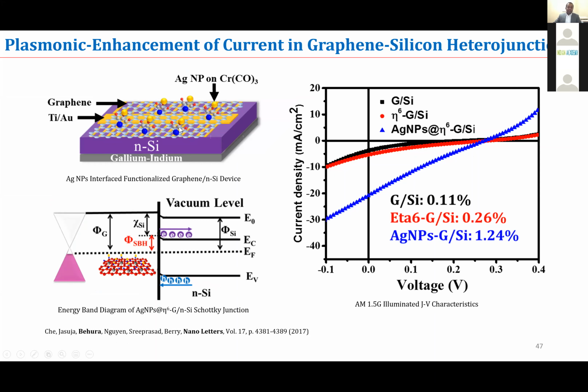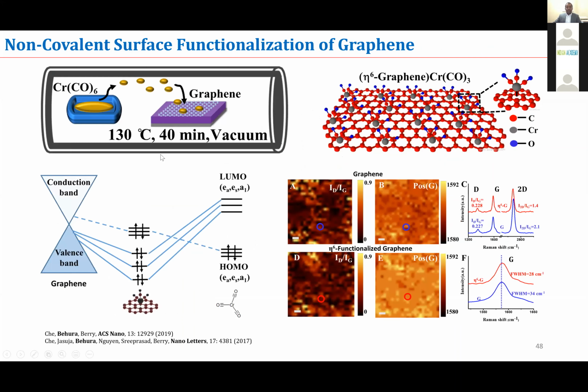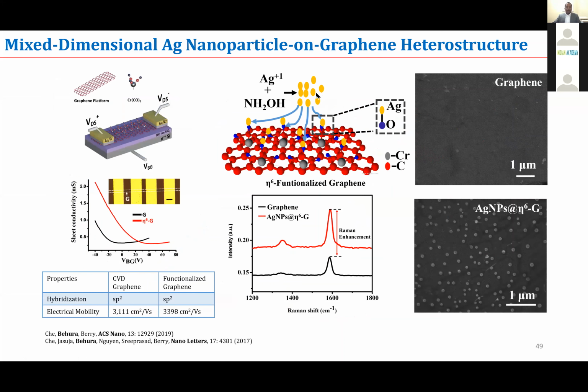So these devices are not only useful for solar cells, they can be useful for many other optoelectronic devices that are currently being studied. And here is the process of how you can use metals on top of graphene, because graphene is thought of as a chemically inert structure. If it is pristine, it will be difficult to put a metal on any hexagonal ring. However, we can functionalize without creating any defects in the structure, and then we can anchor these metals in order to enhance the current by absorbing more light from the sun. And this is how you can anchor the silver nanoparticles on top of graphene. You can see your functionalized graphene anchoring silver nanoparticles, your unfunctionalized graphene anchoring silver nanoparticles.